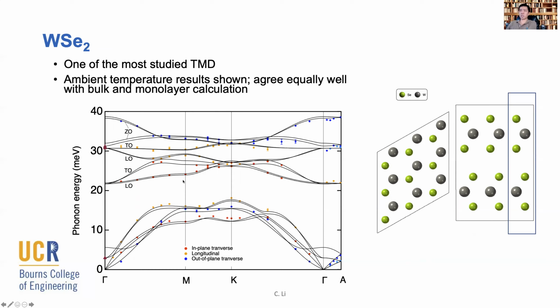But before I go any further, I want to highlight one important observation we had. Here I'm showing a DFT calculation versus our inelastic X-ray measurement. If you dig up the literature, you realize for this tungsten selenide system, most of the DFT calculations were performed for a monolayer. And it turns out if you do the same calculation for a bulk, our observed inelastic scattering result agrees equally well with the monolayer calculation. So what I'm saying is, we cannot tell from our inelastic X-ray scattering measurement whether the agreement with monolayer or bulk is better. That tells you how close phonons behave in those two types of systems.